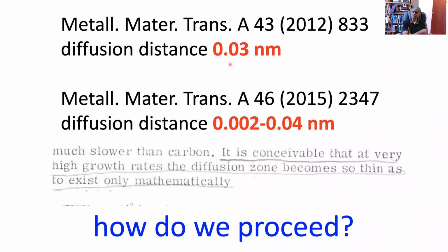When you have this negligible partitioning local equilibrium mode, the diffusion distance is unphysical. There's no possibility of defining a concentration spike at the interface which is that small.